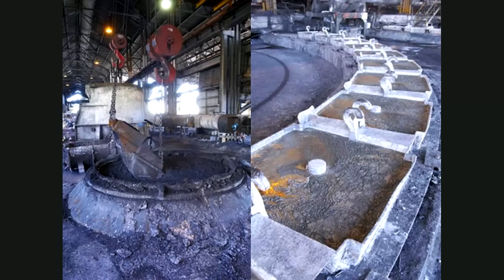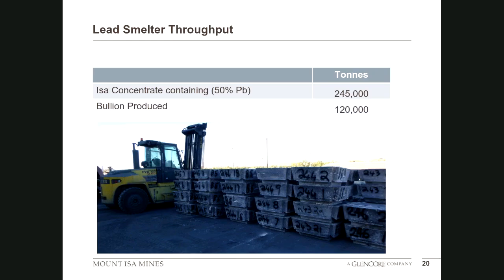mixtures take place. Then what you do is you do some semi-refining, you upgrade it, and this adds a little bit of caustic, so sodium hydroxide, and then you create lead blocks from this product. And this is about 99.7% lead. This is then labelled and is transported to BRM, so British Refined Metals, in London. So we produce about 120,000 tonne of it each year, and normally we treat about 245,000 tonne of Isa Concentrate. So yeah, that's in essence the presentation.